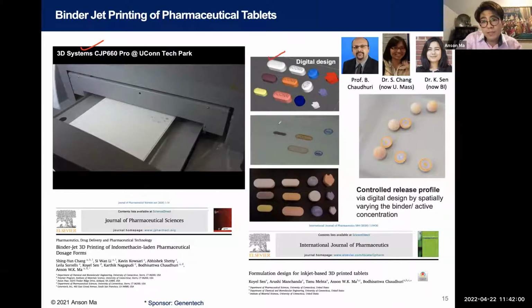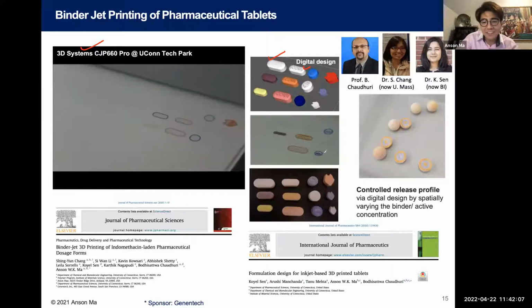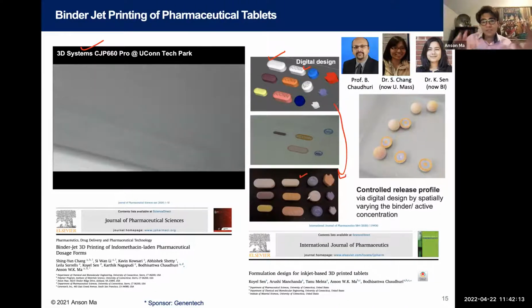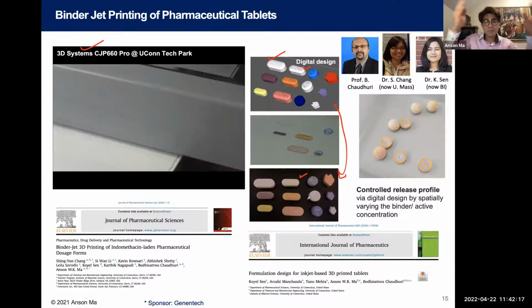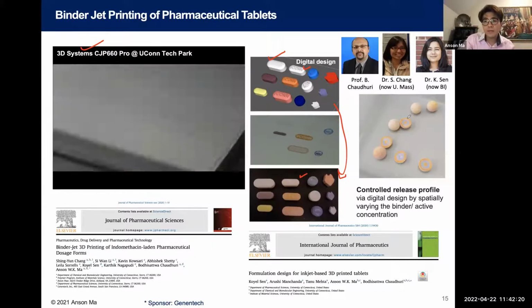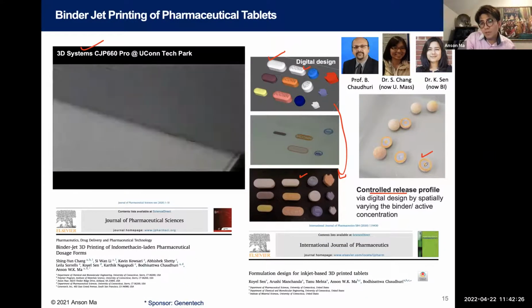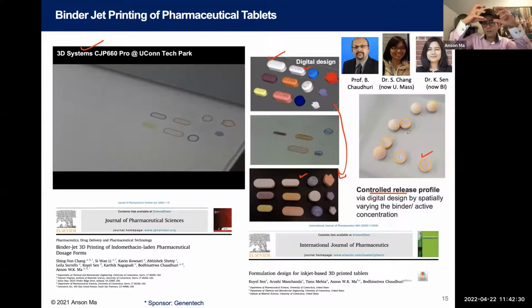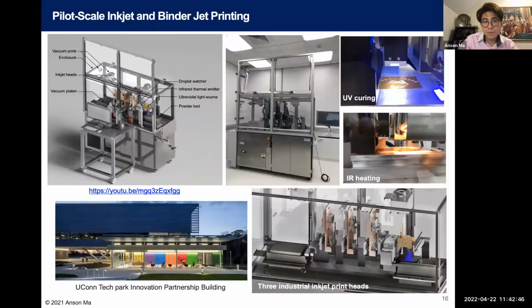And then you can go from digital design like this. You see a lot of UConn Huskies, not surprisingly, since the Husky is our mascot for the sports team. We can convert something from a digital design to various designs. It's very flexible. You don't need to change the mold or anything. You just change the digital design, and if you have the right formulation, you can print. And this is what I was talking about earlier, right? By doing this digitally, you can also change the design so that you can have these concentric spheres. I pretend that the orange color is one drug and the blue is another drug. So you can do sectioning, right? You can do A, B, A, B. And then by the time of release, it will also come out in an alternating sequence. That's the beauty of doing printing for pharmaceutical.